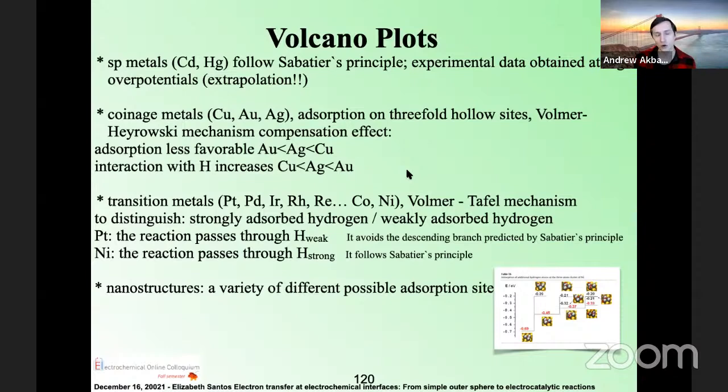So even if we have a copper monolayer on gold, we can have copper orbitals, but the gold density of states. Isn't that a way to decouple it? Good. We have also tried that. Some of it I have shown very quickly, but we have investigated different substrates and put another metal that could be more active, but that also changes the distance between the neighbors of the metal.